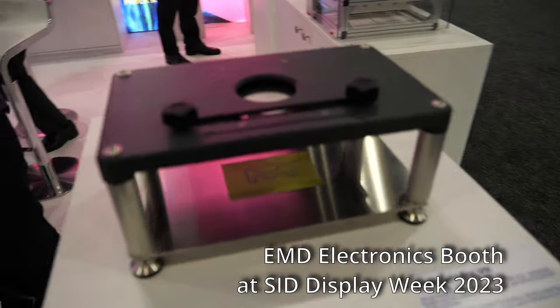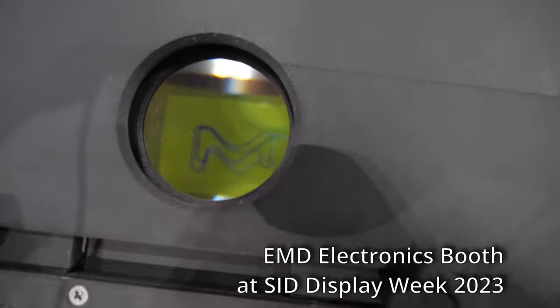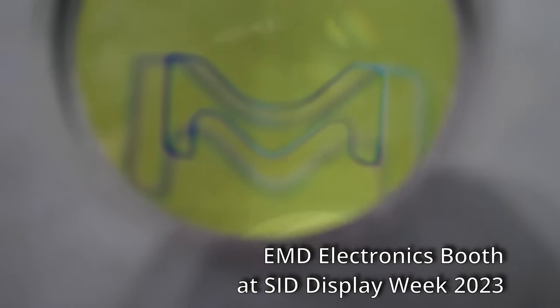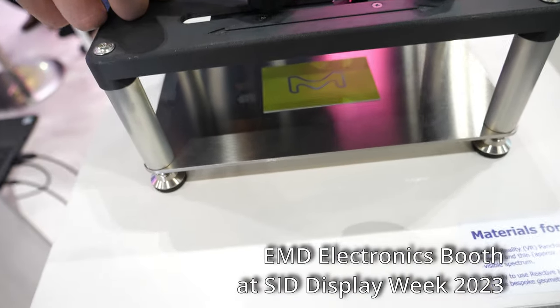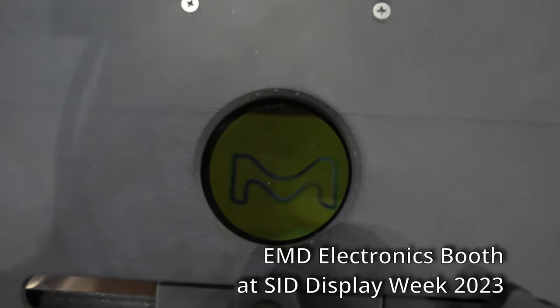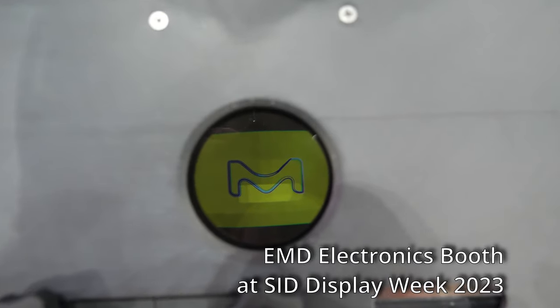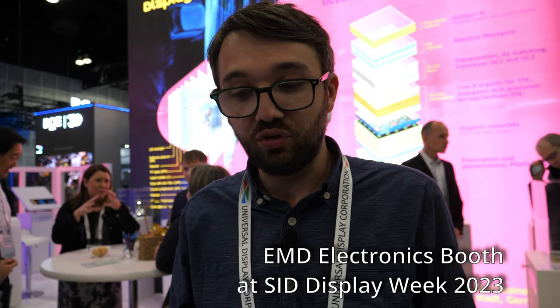And what do we have here? This demonstrator uses the same technology — also a polarization volume hologram, also referred to as a Pancharatnam-Berry grating. You'll see two images, neither of which are actually the true size of the image below. If we slide in one of these circular polarizers — left and right handed polarizers — it selects for a magnified and a demagnified image. If I slide out one polarizer and slide in the other, you'll see this image is now small, and then move back and the image is enlarged. It's the same grating, it doesn't move. This is about an ultra thin layer — approximately one micrometer thick — and it allows you to create lenses that are ultra thin and lightweight.